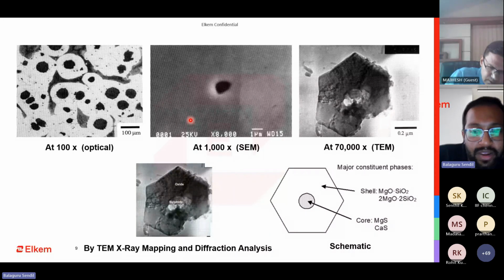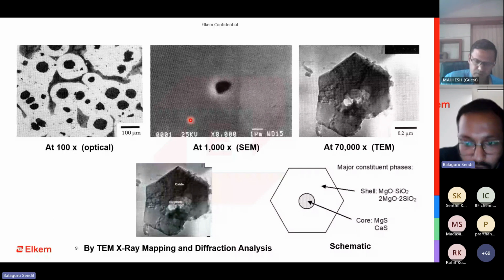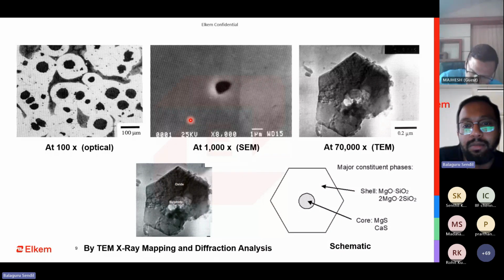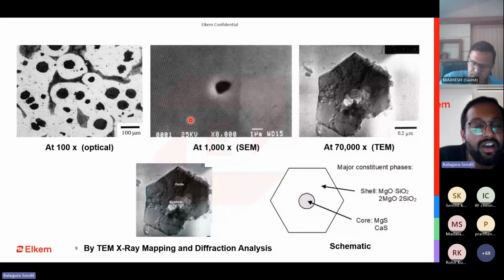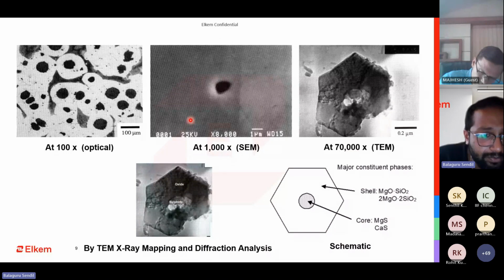So this is the way we see from Elkem, how does the nodularization process happen, and also what is the core of a nuclei and what is the shell of the nuclei, and how this is actually helping in making sure that the carbon is coming and settling down there and it is growing to the correct size and shape. You don't want to have a misbalance in this growth rate, otherwise you will end up getting degenerated nodules which will not have good mechanical properties.